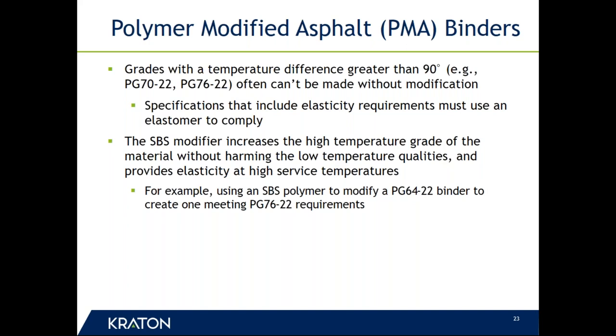In order to assure that you're getting polymer modified binders, what many specifiers have done, like TxDOT has, is to include an elastic recovery requirement or MSCR recovery requirement, or simply state in the specification that you will use an SB or SBS modifier in order to achieve specific grades. The Florida Department of Transportation and Georgia DOT do something like that. What the SBS modifier does is increase the high temperature grade of the material without significantly affecting the low temperature qualities, but probably more importantly, it does it by providing elasticity at high surface temperatures. I have a video coming up that will illustrate that visually to you.